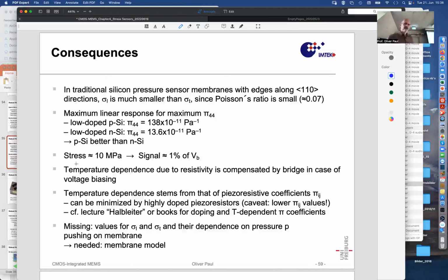And if we have stresses of about 10 megapascal, then we also know that the signal will be about 1% relative to the input voltage. And then the nonlinear part will be 1% of the 1% roughly. The temperature dependence due to the resistivity is compensated by the bridge design if the bridge is operated in the voltage biasing mode.